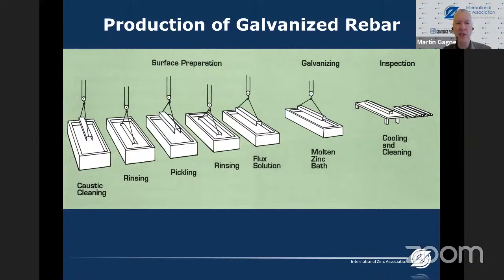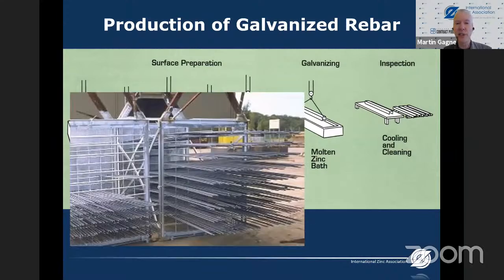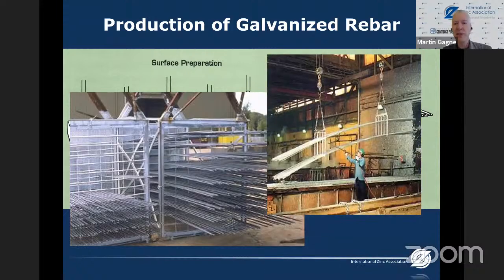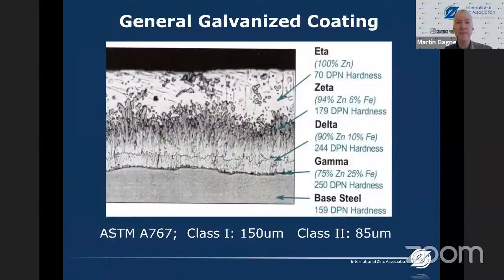Now, the production of galvanized rebar is the same as for the production of any galvanized product. We clean the steel, we pickle it, we flux it, we immerse it in molten zinc and then cool it. If there are any galvanizers in attendance, the main issue really is racking, it's material handling to separate the bars so that they can be galvanized cleanly. But this is really quite routinely done, and there are no special considerations apart from racking for galvanizing reinforcing steel.